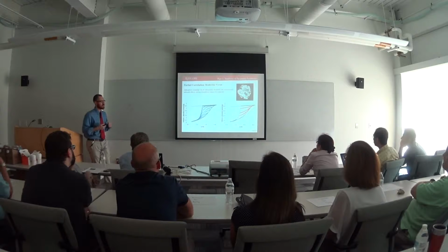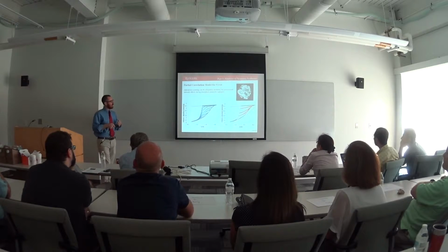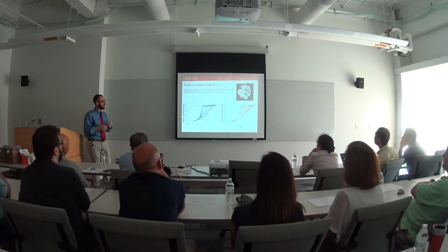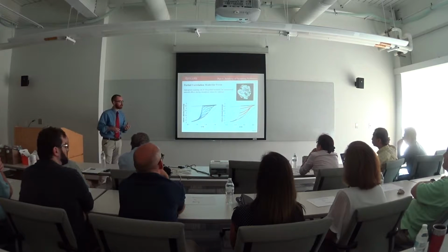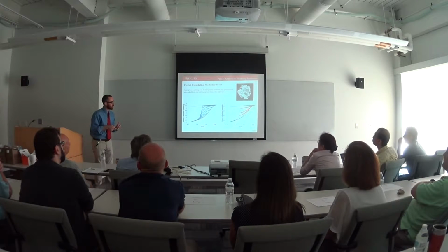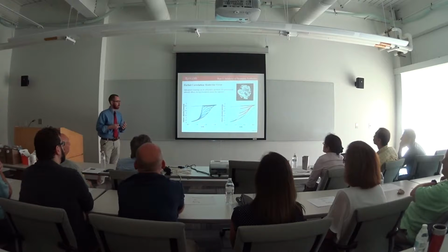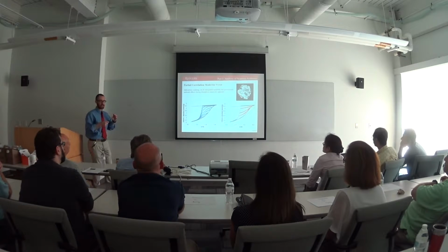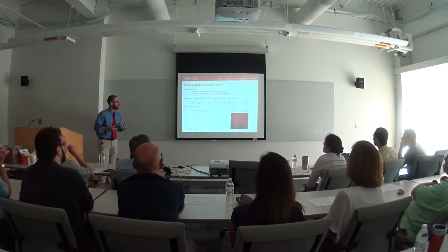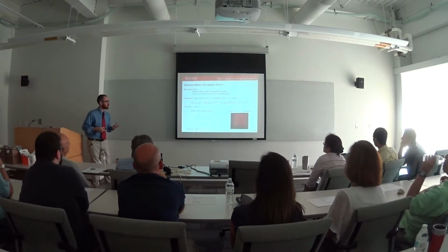Okay, so the partial correlation model can also be used as a probe for porous materials which are disordered. This picture here is a schematic of Vycor glass, which is a highly disordered porous material. And as you can see, these are adsorption scanning curves on this material. Everything works very well in the partial correlation model. However, on desorption, we see that the model fails pretty spectacularly. The reason for this is that we don't have these independent domains for pores. They're all interconnected. And so, in order for us to accurately capture network effects, we have to introduce something called percolation theory.